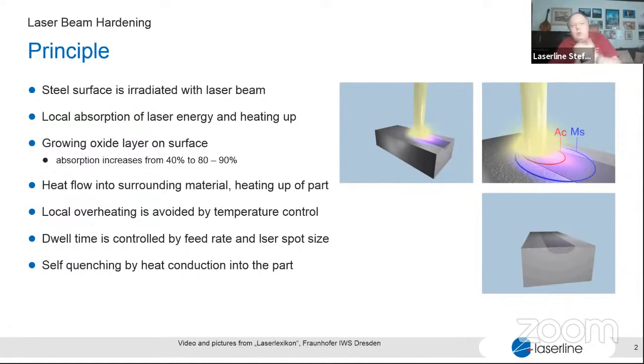On the other hand, the absorption of the laser depends on the material, depends on the surface condition of the material. So if you have a very shiny steel part, then you have 40% of absorption. If you allow the oxidation, then you have 80%. So that makes the difference. If you do a post-treatment by milling, grinding, whatever, you can usually allow the oxidation and you have a very, very highly efficient process, allowing the 80% of absorption.